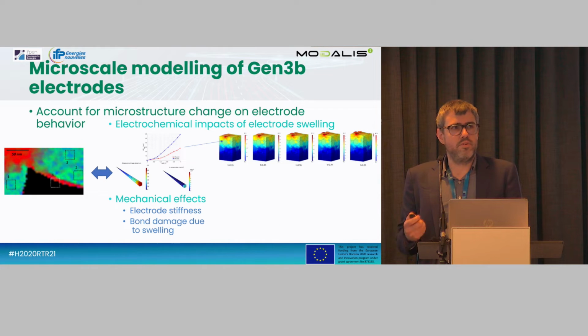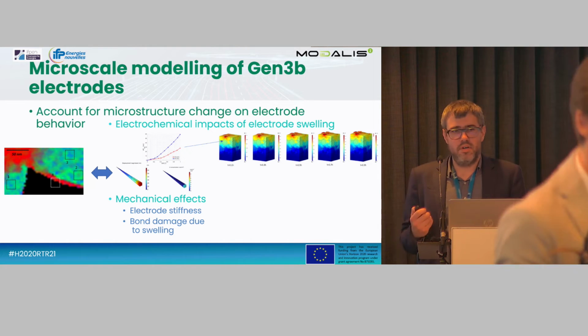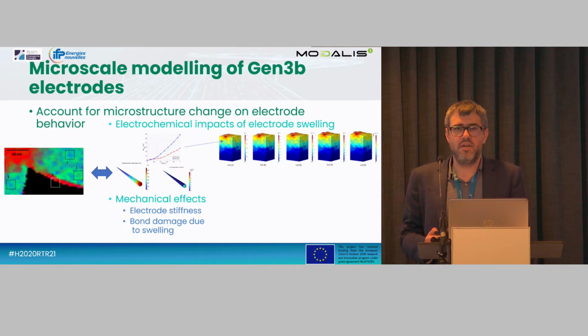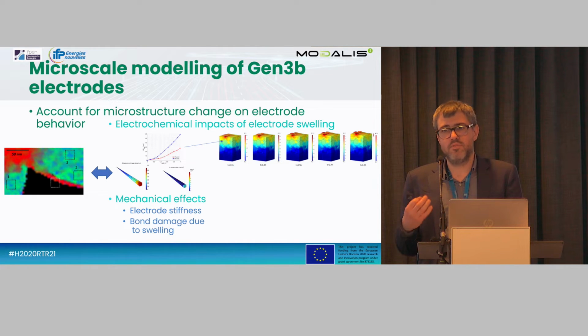Then the second focus was to understand the mechanical behavior of the cell. And this is also a multi-scale step because there is a lot of complexity in the materials that we are using in the negative electrode. So first, based on the TEM analysis that we did on the material, a specific work has been done to recreate this in FEM in order to understand the behavior of the composite material that is composing the particles of the electrode. This allowed us to understand how the particle was swelling in order to put it into a complete 3D FEM model to understand the swelling of the electrode and the electrochemical behavior resulting from this swelling.